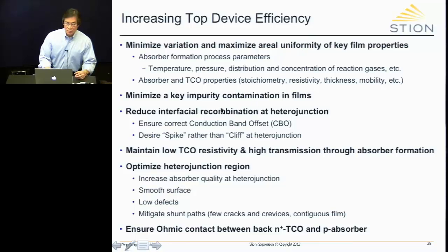Number two, it turns out that there's a key impurity for wide bandgap chalcopyrites that will kill you. We have to minimize that. Number three, we have to reduce the interfacial recombination. Number four, we have to maintain the TCO properties through the absorber formation, which is a very caustic environment. Number five, we have to optimize the heterojunction region. And number six, we have to ensure an ohmic contact to the back.